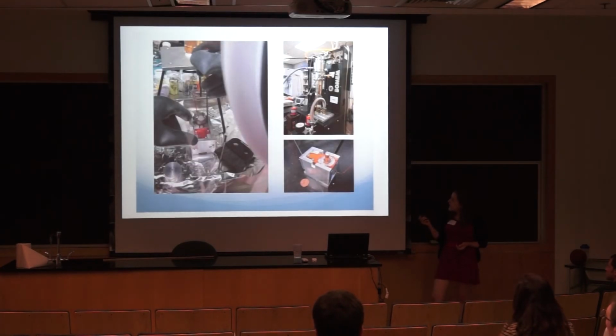So here are some pictures of the lab. This is the spectrometer with the cryostat on top of it. Here's what our sample actually looks like. It's just a powder, a very tiny amount of powder, and that's a sample holder. We have to do everything under an atmosphere of argon because the sample is very, very air sensitive. If you exposed it to air, water from the air would just stick to all the metal sites, and then you'd never get hydrogen to stick. So we do everything in a glove box and then attach this dome to the sample, and it has windows here so that the infrared light can go through.